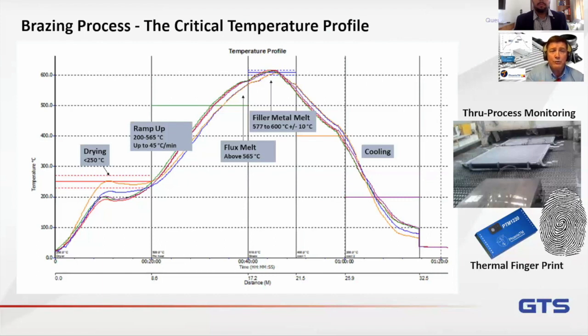So you can do multiple points of measurement, up to 10, or in some cases even up to 20 if you wanted to. That's a bit overkill in my view, but we're achieving the same profile. And from this profile, that thermal fingerprint will tell you how your process is working. It's unique to that furnace, and it's unique to that product on that particular day. So it gives you a snapshot or a golden template of how your process is working. A picture, let's say, of what your process actually is. Yeah, and that data can be invaluable to understand possibly when things are going wrong in the process, as we'll discuss in more detail later. Correct.